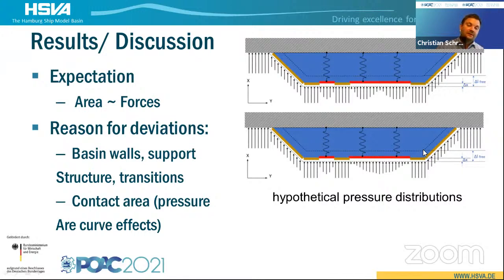So all the stiffness part will be together, and you must think about how the pressure area curves or the pressure curves in the different areas might be. So we put up some hypothetical pressure distributions, how we can imagine that the pressure is distributed. So this will also be a matter of further study and discussion, how the loads we now measured can be interpreted, and also probably which kind of setups could be optimized for future test conditions for thermal ice loads. Also now comparing the small plate with the bigger plate with an area ratio of 4, of course, we come into the area where the pressure area curve takes some effects. So also these effects should be taken into account.